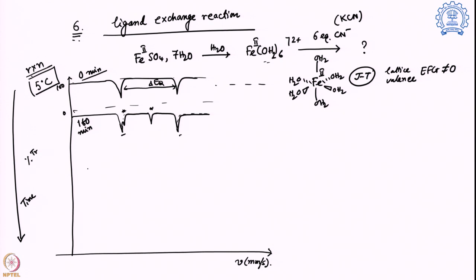Then we run that for almost 12 hours keeping it at 5 degree centigrade, and the data we are getting is the following. The original position is very limited. So, obviously, the original iron hexahydrate sample is going out. This data we saw earlier. Let me draw that in a different color so that we can follow that also. That particular signal starts increasing in size, and very interestingly we also found there is another signal generating on that side. Let me put that in the green line. So, another signal starts showing up over here, but that is a singlet.